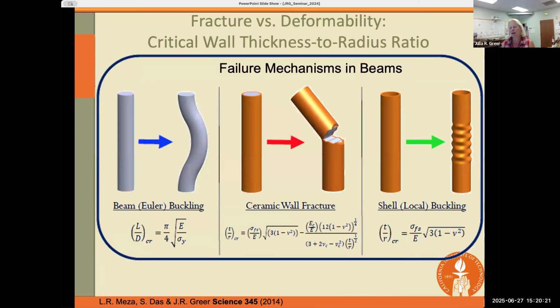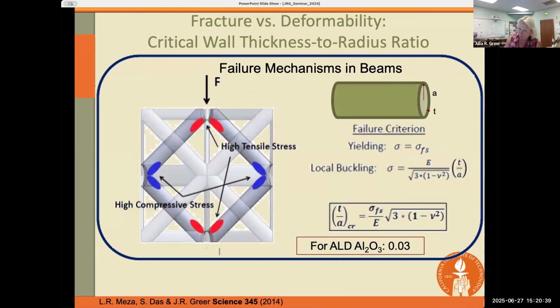Now, of course, to try to understand why this happened, we turn to mechanics, and one type of deformation that allows for this kind of recoverability is called shell buckling. Imagine your soda can, right? You create some wrinkles in the surface of the hollow cylinder, but then you have the ability to recover. When you perform this calculation, it turns out that there's a critical t/a ratio, the ratio of the wall thickness to the radius, which for this particular material, ALD alumina, turns out to be something like 0.03. So if you're below that ratio, your structure is able to recover based on this shell buckling criterion. Above this ratio, your material will fail prior to the structural response.